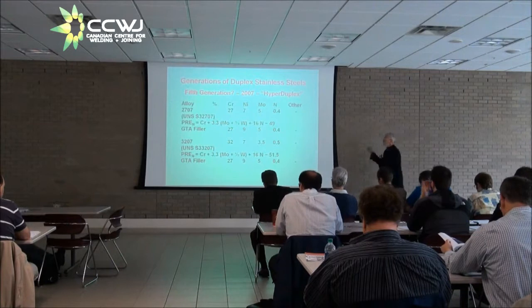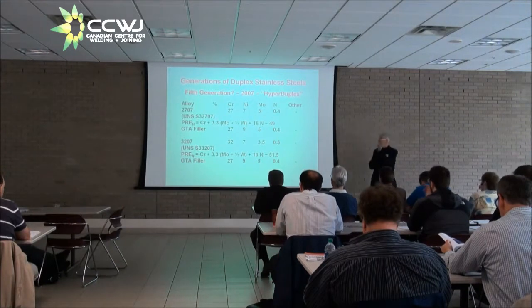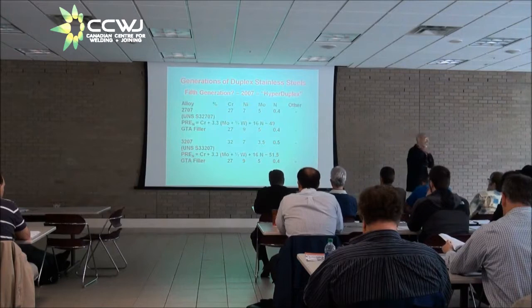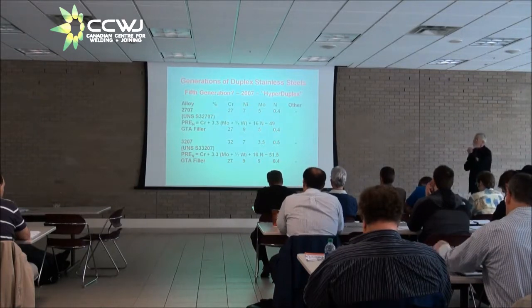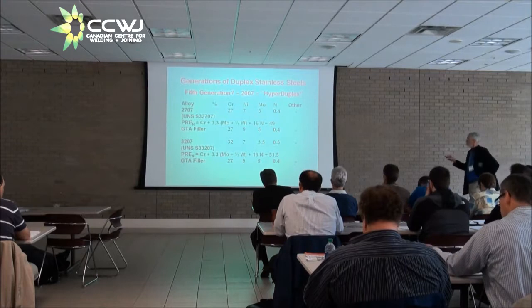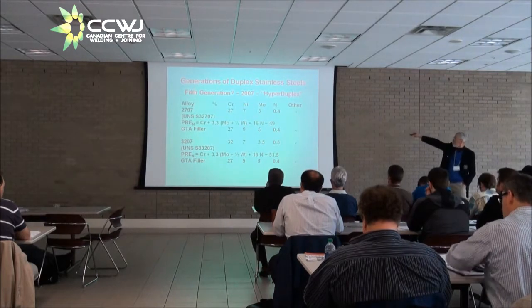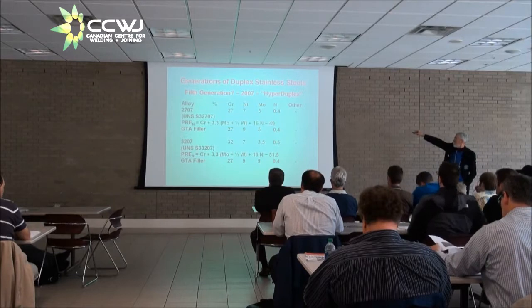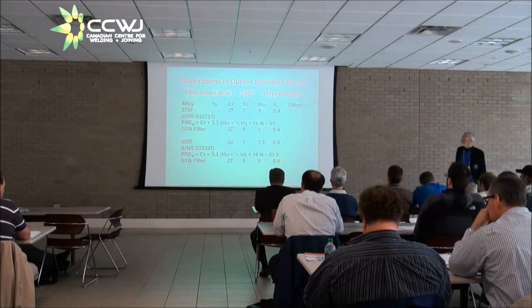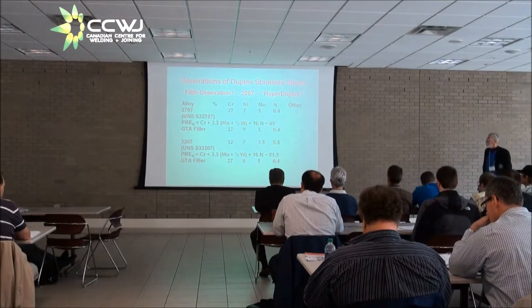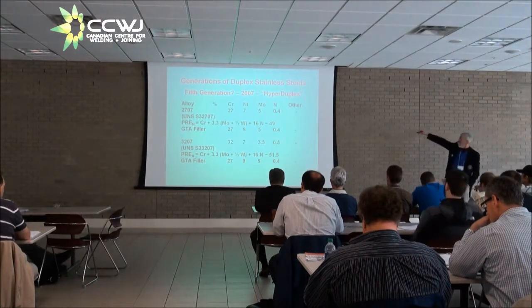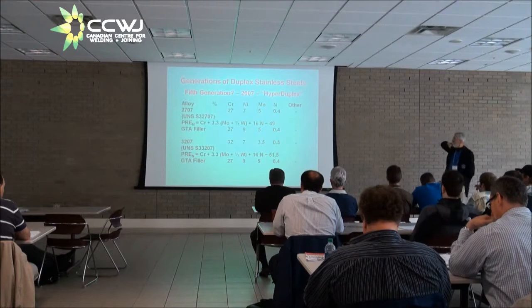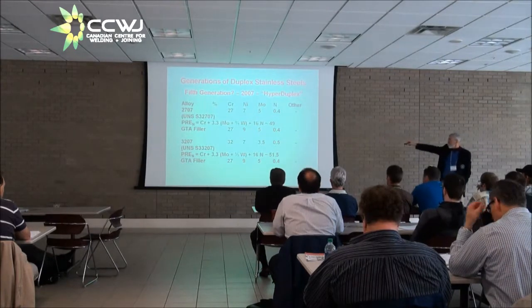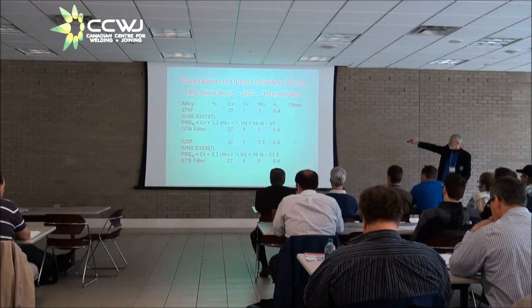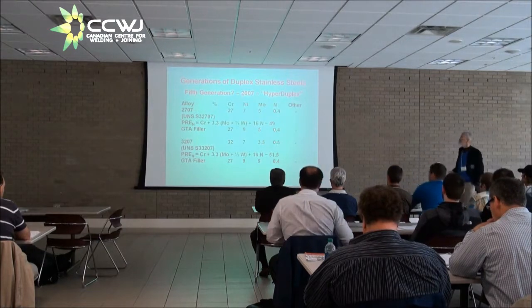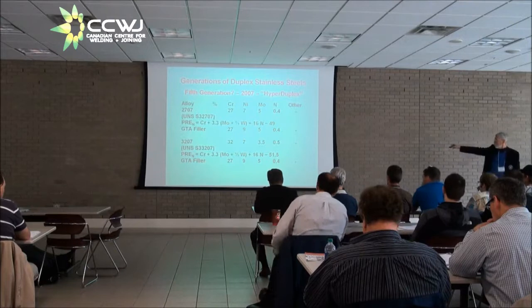Now, we talked about hyperduplex. That was mentioned again this morning. There are two hyperduplex alloys that have seen some appearance in the literature. 2707, which is a 27% chromium, 7 nickel, 5 moly, and 0.4 nitrogen material, has a PREN that doesn't quite make 50, but I think that's a little accident that came out with it. And then there's a second one, 3207, which is 32 chrome, 7 nickel, but it's not so high in moly. And that actually does have a PREN above 50.